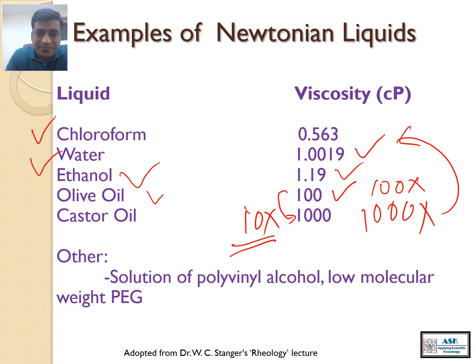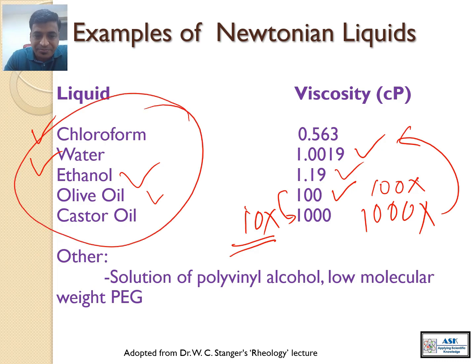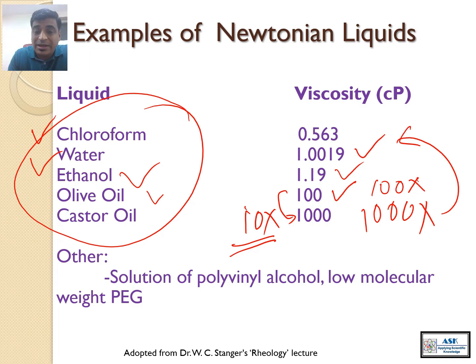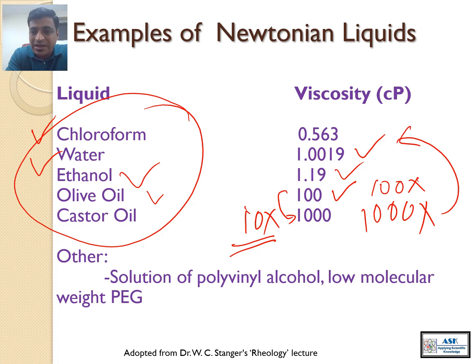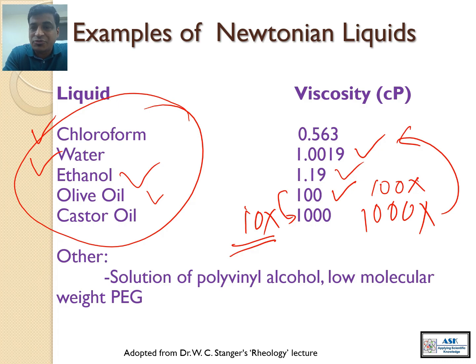Where are you using this viscosity knowledge? If you have to select polymers based on their molecular weight, the viscosity of a polymer changes accordingly. If you want to choose polymers for coating operations in tableting, you need to find out the molecular weight and the possible viscosity of that solution, because too viscous a solution will not go through spraying guns and you won't be able to coat any tablet. So even in solid formulations you need to know viscosity.